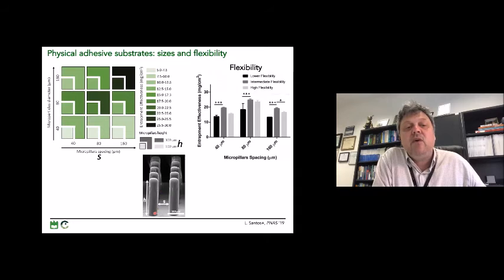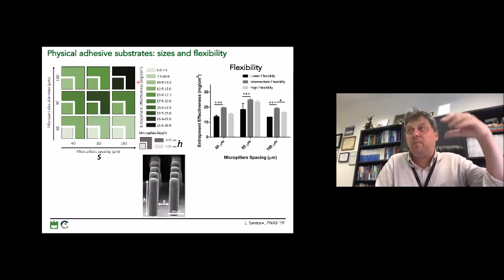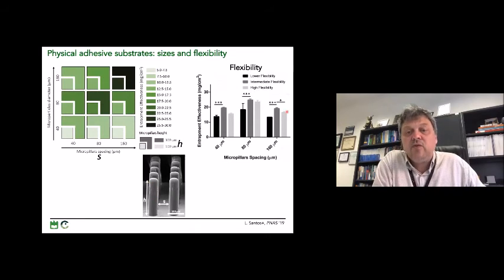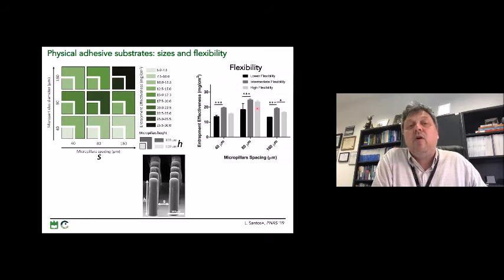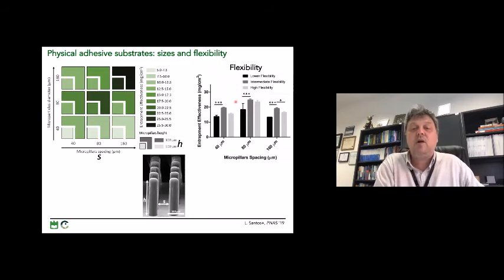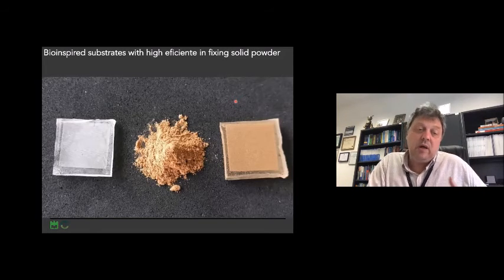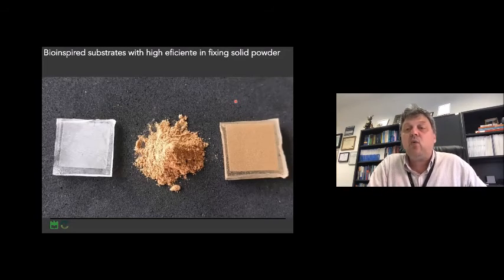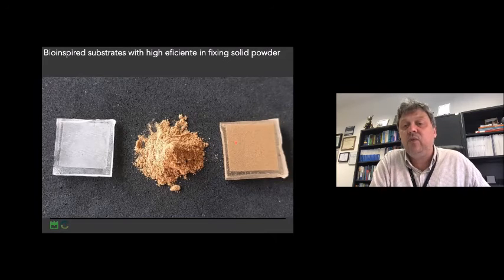It's also clear that depending on the height of the pillars, so we tested 100 and 300 micrometers, when we have 300 micrometers, we have more efficiency of entrapment. And this is because you have a much better packing of particles, so you can accommodate more particles if you have taller pillars. We also analyzed the influence of the flexibility of the pillars on the entrapment efficiency by controlling the elastic modulus of the elastomer of the membranes. And we could see, for example, that intermediate flexibility fixed more particles. So we believe such platforms are really adequate to physically fix high quantities of solid particles or powders by tailoring the arrangement of the pillars, so the distance and the height. Even after shaking a membrane that was put in contact with this kind of brown powder, the entrapment of the microparticles on the surface is really efficient.